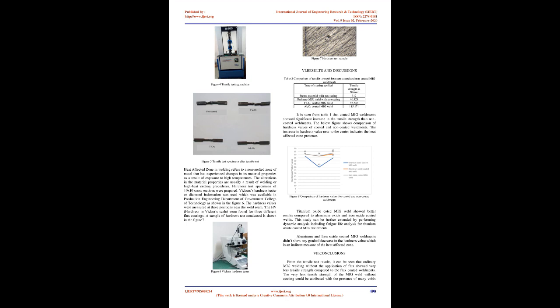Tensile tests were conducted for 5 samples, namely ordinary MIG weldment, Al2O3 coated MIG weldment, Fe2O3 coated MIG weldment and TiO2 coated MIG weldment, and for the parent material, using the Universal Testing Machine facility in the Production Engineering Department of Government College of Technology. It was observed that for the ordinary MIG weldment, the necking happened at the center of the weld seam, whereas for flux-coated MIG weldments necking was found at areas near the weld seam.